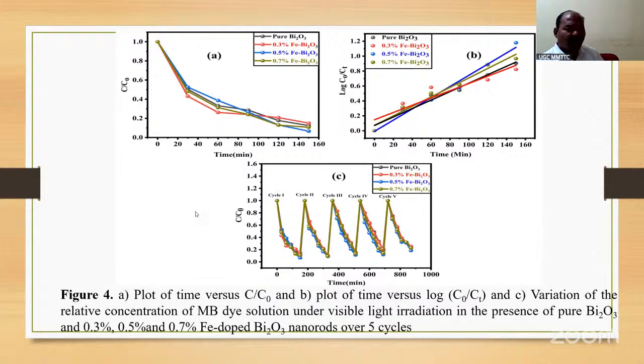Now this is the plot of time versus C by C0, and the plot of time versus log, the variation of the relative concentration of methylene blue dye solution under visible light irradiation in the presence of pure and these nanorods over the cycles. Now C by C0, this plot is for pure, then 0.3% iron doped bismuth oxide. This is red 0.3, 0.5 blue and 0.7 this.